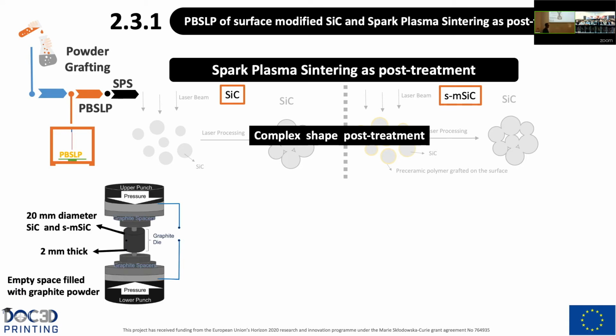Here we have the setup of the machine. Again, we manufacture 20 mm diameter silicon carbide and surface modified silicon carbide pellets with the powder bed selective laser processing, with 2 mm thickness. And actually, in the graphite die, we are going to fill the empty space with graphite powder.